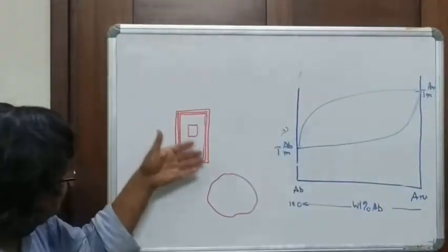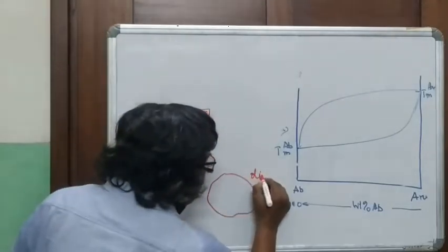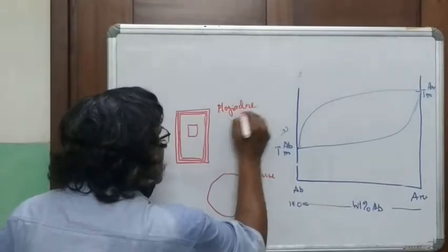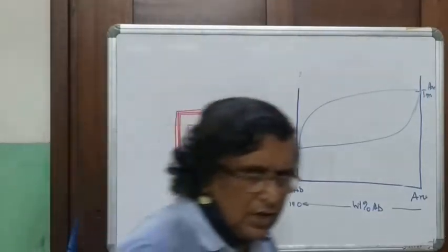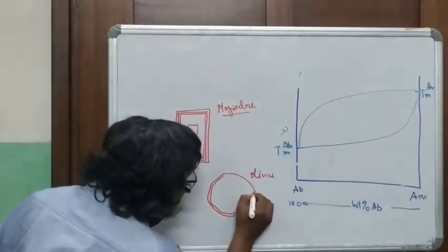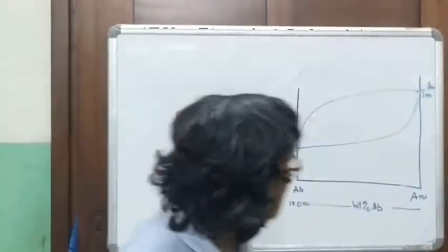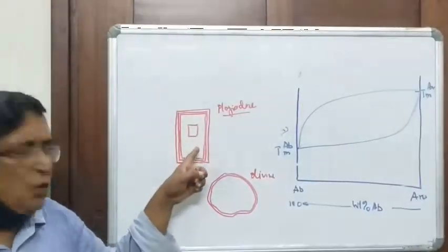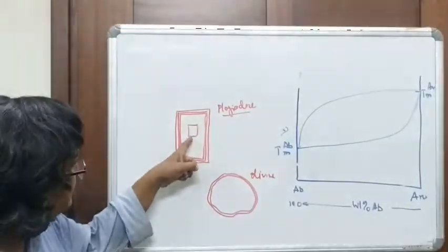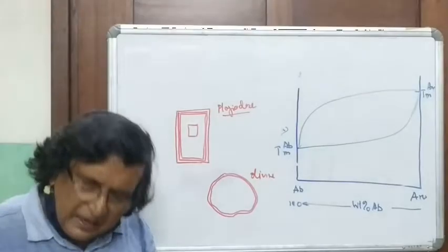If in a rock you see both olivine and plagioclase, you will see plagioclases are almost always zoned, and olivine is almost not zoned. And if it is zoned, most of the olivine zoning is restricted to the margin and is very weak. But plagioclase crystals are zoned. The margins are very strongly zoned, but the center of the crystals are much less strongly zoned.